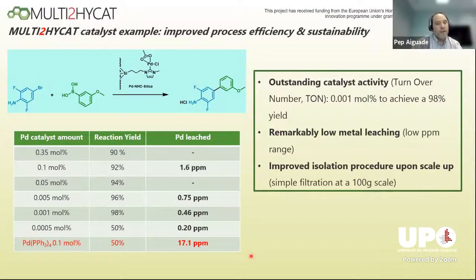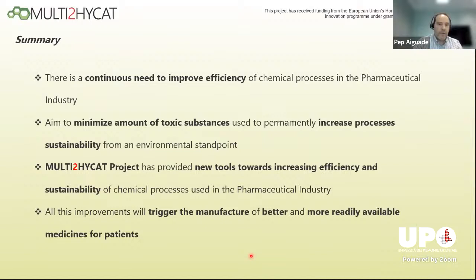So with this catalyst that has been tested and synthesized in this project, we have obtained a catalyst with outstanding catalyst activity, remarkably low metal leaching, and a very improved isolation procedure. Even at 100 gram scale reaction, just a simple filtration will recover the catalyst, so we can reuse it for another reaction. So again, an example of process efficiency and process sustainability.